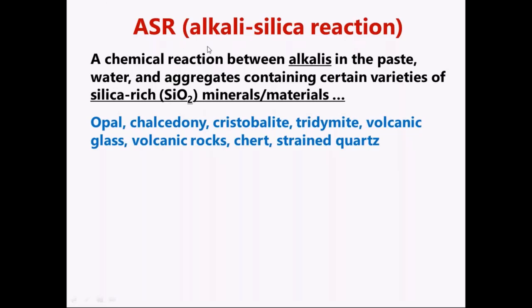Again, this is a reaction that's occurring between the alkali in the paste, water, and aggregates that contain certain varieties of silica-rich minerals. So here in blue, I've listed the silica-rich minerals. What they all have in common is SiO2.